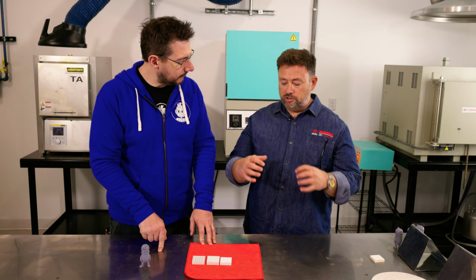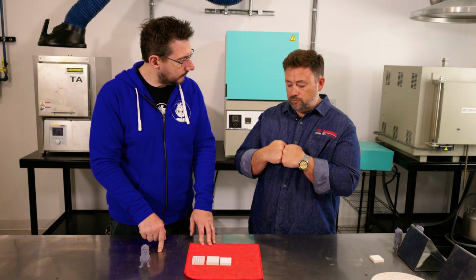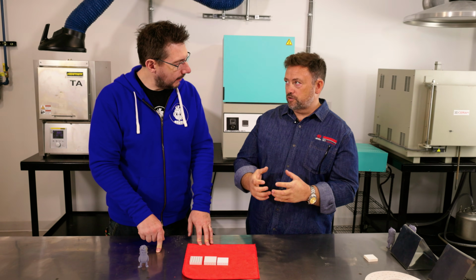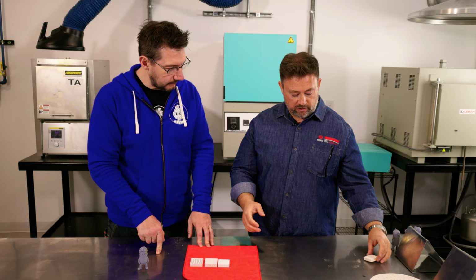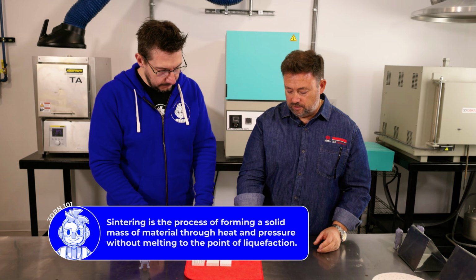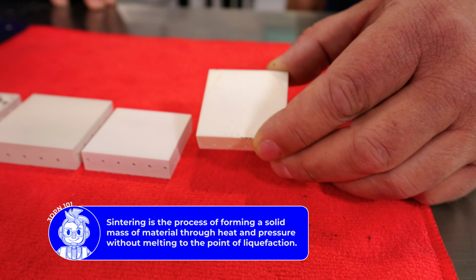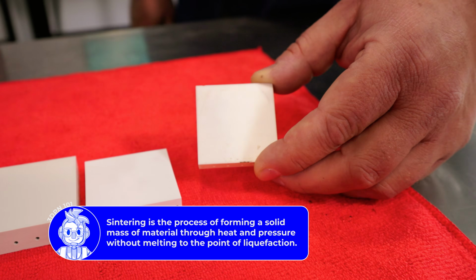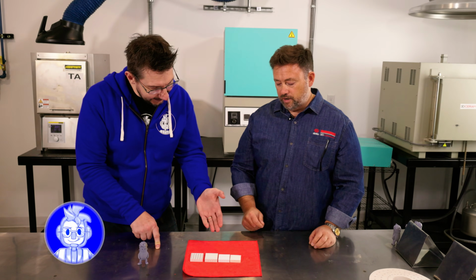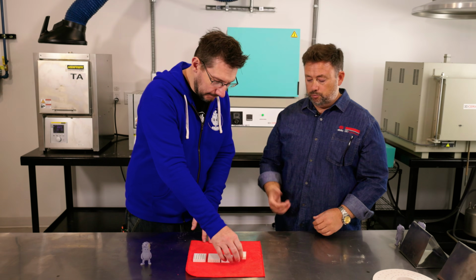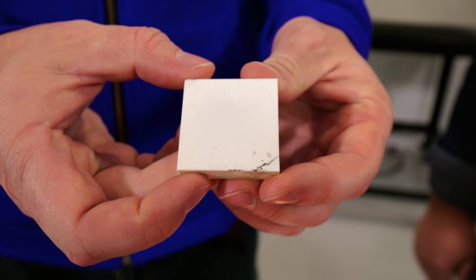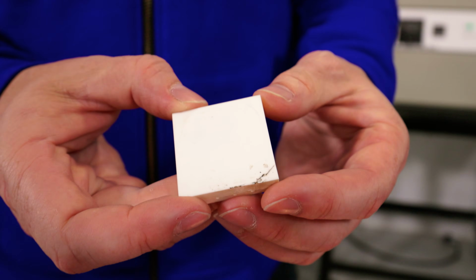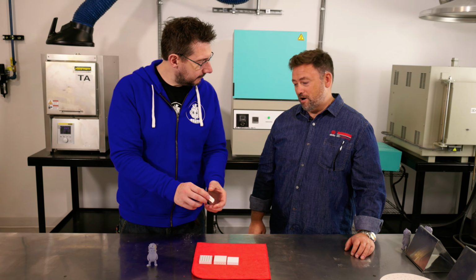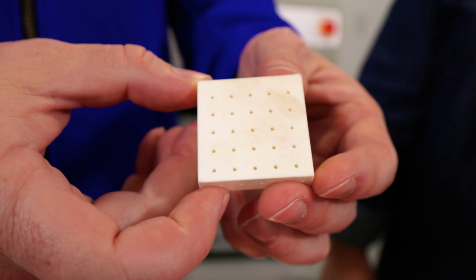And then what we're going to do is start that process of fusing the ceramic together, called sintering. And once we fully sinter, you will end up with a piece that looks like this. And this piece, as you'll see, is quite a bit smaller. It's even smaller. May I? Yes, and this one would be a hard, dense ceramic. This one has been tested and fired. So that one has got some marks on it, some scars from actually being through a thermal test, a torch test.